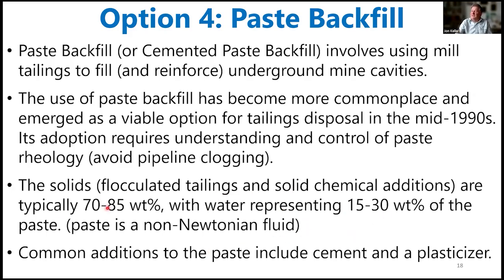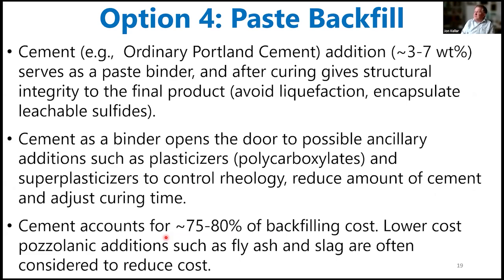Now, if you meet those guidelines, the paste is what we describe as a non-Newtonian fluid. It needs to be pumped around. Common additions to the paste include our friend cement and a chemical addition called a plasticizer. And that cement addition is typically in the 3 to 7 weight percent. It will serve as a final binder after curing and give structural integrity to the filled cavity, where you're trying to avoid liquefaction if you can.